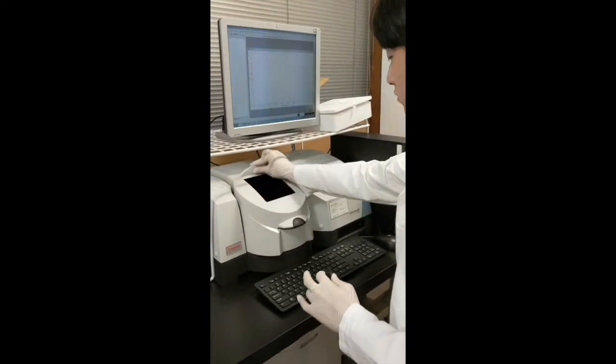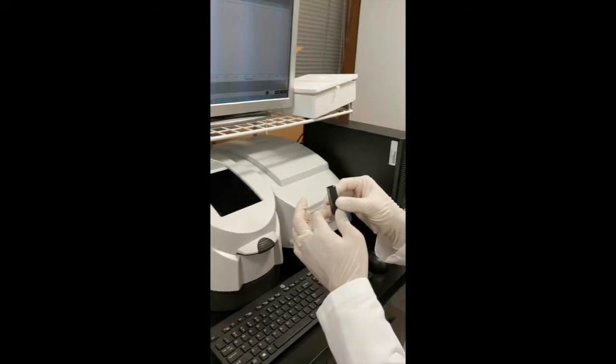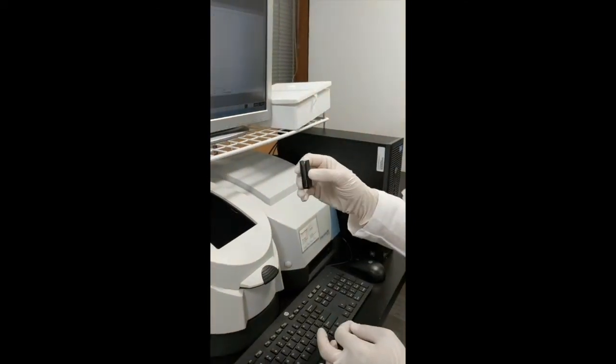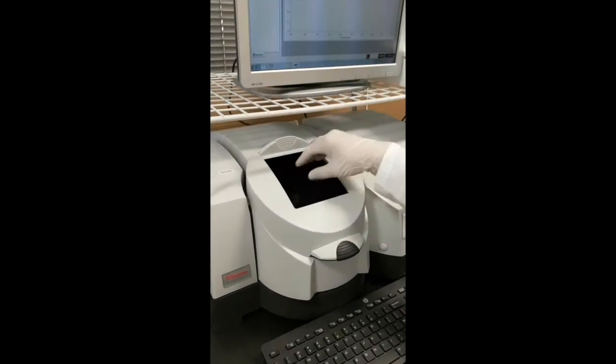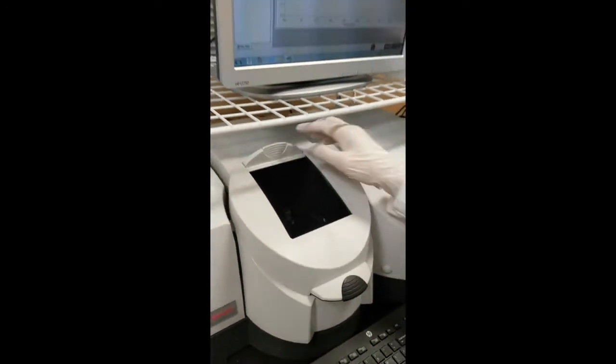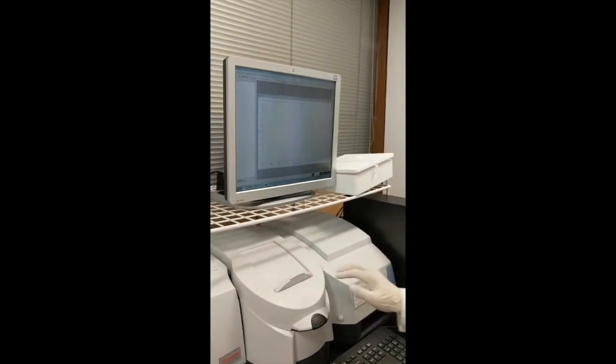After purification, we characterize the purified product. UV-vis spectroscopy is used to measure the relative amounts of PIC and nanoparticle in our conjugate system. This is important for dosing calculations for treatment experiments.